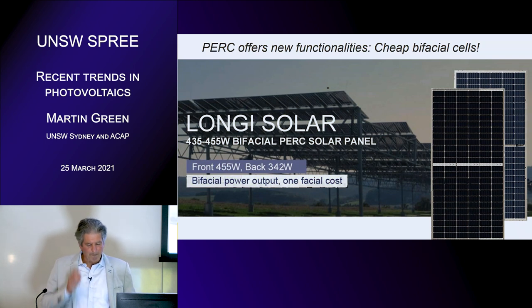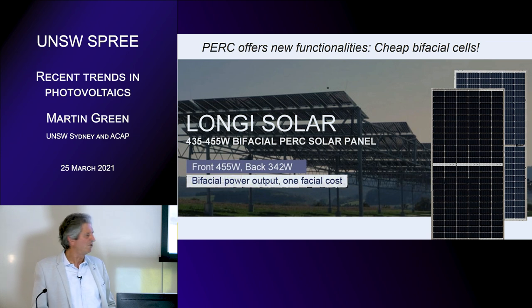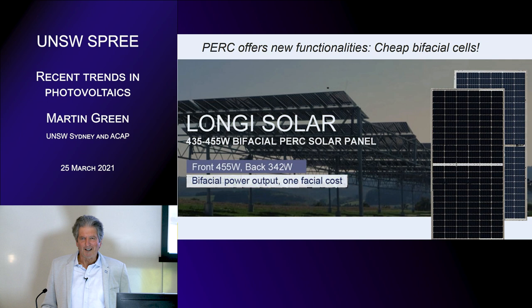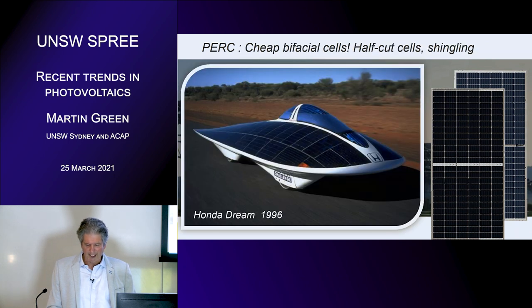So that gives you extra energy for free. That's at least a 5% gain without doing anything too spectacular, and you can get up to 20% if you take a bit of care, having reflective, white painted backgrounds or white stones in the background or something like that. So that's been one thing that's taken off in parallel with PERC, bifaciality, which has added to the cost reductions.